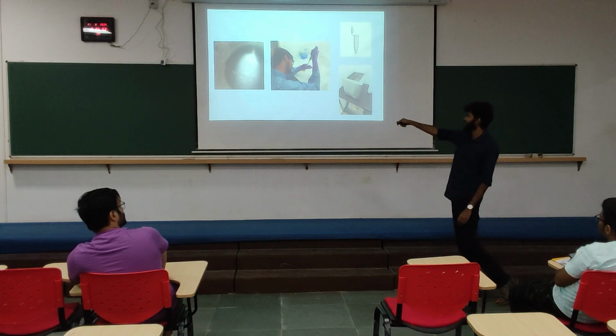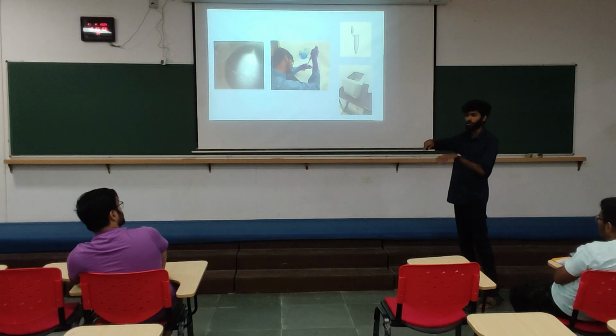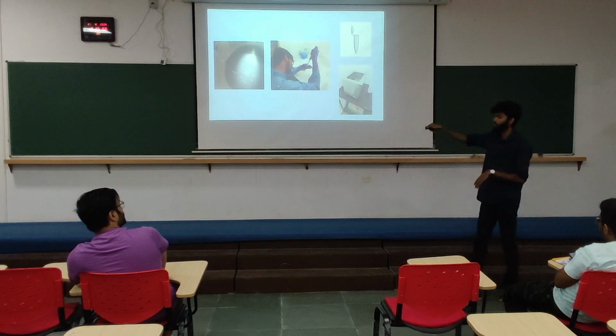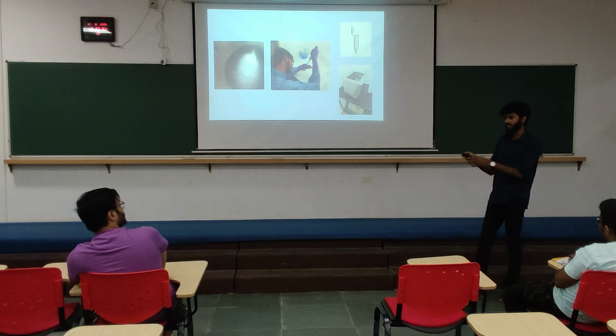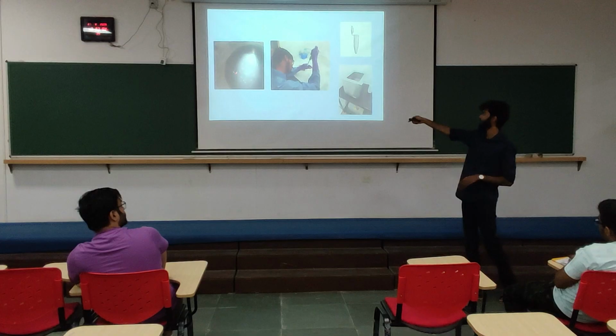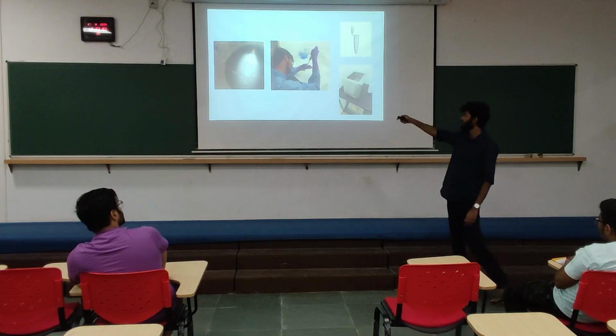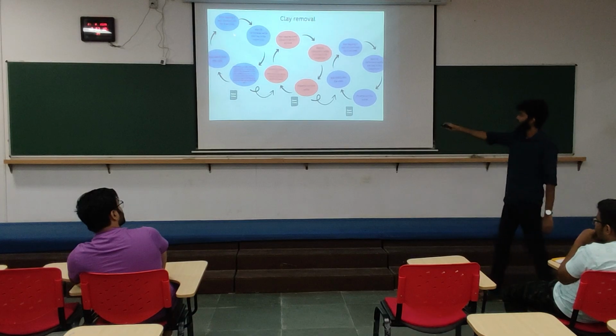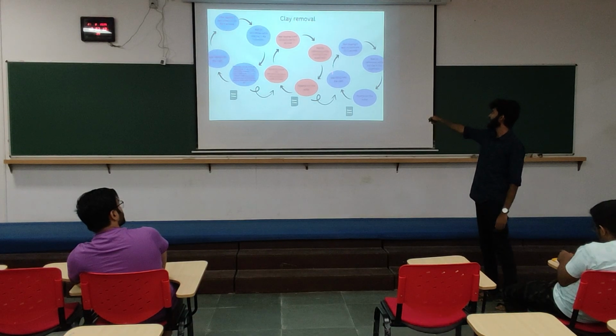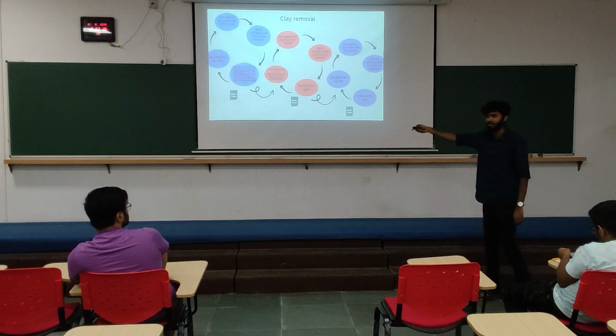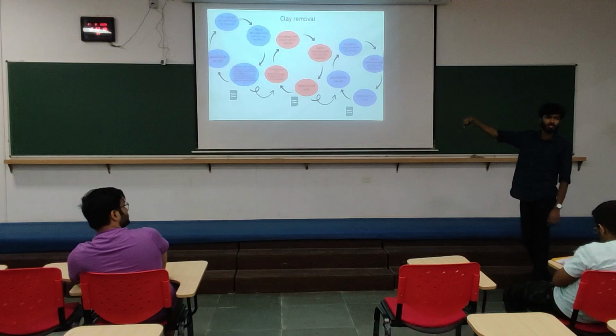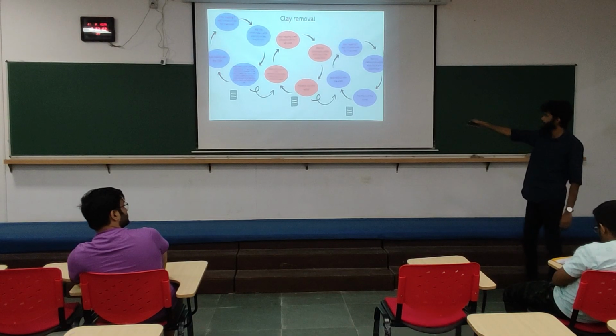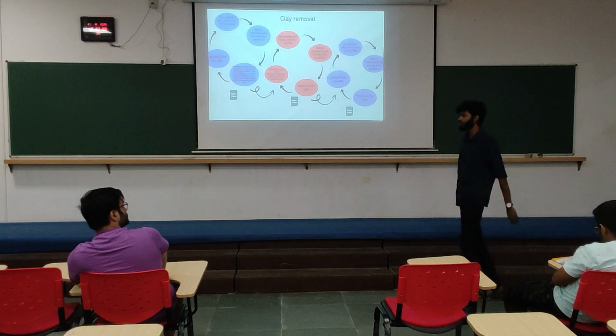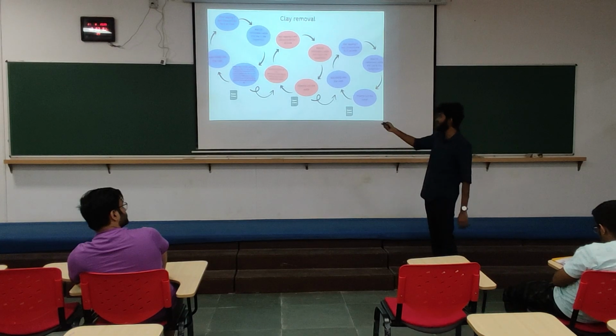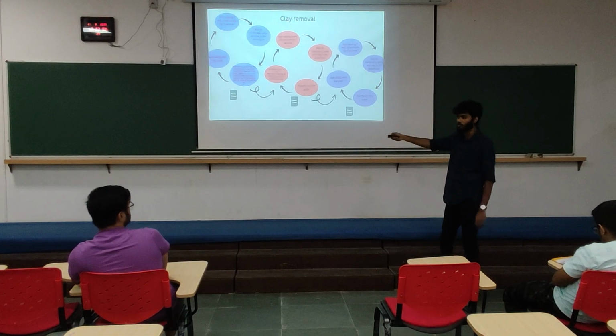So here is a picture of cracking of foraminifera. I was talking about foraminifera and corals. Corals are in powder form, but foraminifera we have to break before doing this clay removal. So this is that process. We use a syringe and microscope to do this. I talked about water. We have to do this 3 times, and then we use methanol. Methanol is even less dense than water, so it will be more effective in that suspension process. Repeat this 3 times, then again repeat this 3 times. It will take almost 15 to 30 minutes for a coral sample to settle down. So it is a really time-consuming process. So this is one clay removal step.